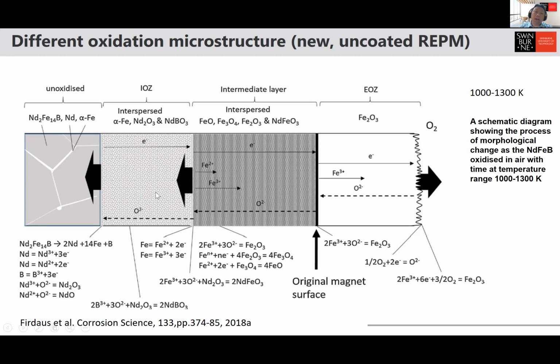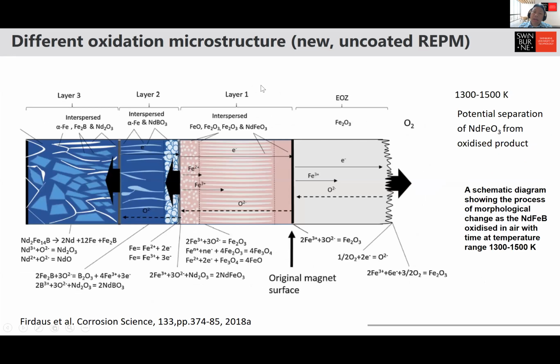So this one here is basically a product of the thermal decomposition as we heat it up before, right? But in here, we have only a small amount of oxygen or no oxygen yet. So it's just thermal decomposition. But as oxygen passes through, it forms this intermediate layer where we started to oxidize the iron into different types of iron oxide. And of course, in the core, we have this unoxidized NdFeB magnet. Heat it up at higher temperature, which is 1300 to 1500, in the outer layer here we started to form quite nice NdFeO3 phases, which are segregated in this layer in the form of lamellar structure with Fe2O3. So this is the basis of our ideas.